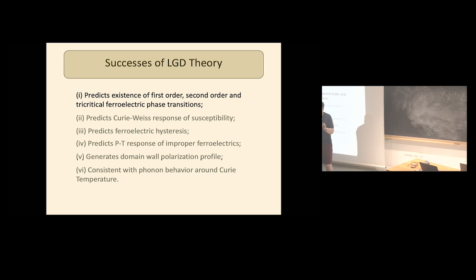So the free energy will be lowered if the electric field and the polarization are both positive. Equally, they can be both negative. But the point is that this minus term requires this to be a positive term when you multiply these two things together. If the field and the polarization are anti-aligned, that's positive field, negative polarization, which gives you a negative number. And then this negative makes that a positive thing, which is adding to the energy. If this is a multiplication that is positive, it's going to be a negative overall, and so that is reducing the energy. That's the mechanism by which we can sensibly allow the breaking of the degeneracy here.